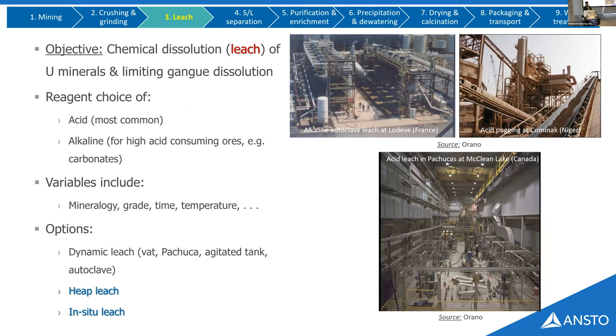So the next step, once you've got your material, as I keep talking about, is leaching. You need to bring the uranium into solution. The reagent choices are, you can use acid, which is very common. The picture that you saw before with sulfur, that's to produce acid on plant that goes into this process. Whereas on the other side, when you have ores that have alkaline and carbonate material, which will consume a lot of acid, you can opt to do carbonate leaching. It will dissolve uranium, but it won't really touch any of the impurities, especially iron. But it's more expensive to use. Again, the variables here, you'll be driven by mineralogy, grade, time, temperature, and the options of equipment.